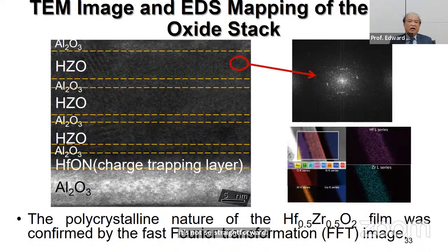In our design we use aluminum oxide and hafnium zirconium oxide all together as a superlattice to make it work, because we need the strain to form this kind of ferroelectric material structure, and we need to design the crystal sizes. If the hafnium zirconium oxide is between two aluminum oxide layers, then the crystal size could be bigger. And also we need to control the stress. Other than that, the aluminum oxide insertion also reduces the leakage current. So there are many advantages of using this superlattice, and for the charge trapping layer, we use hafnium oxygen nitride because it has a higher charge storing capability.